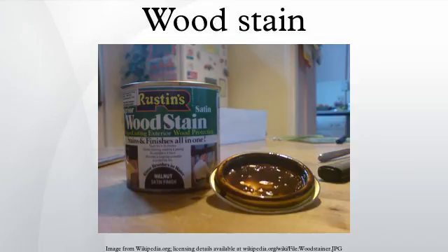Different wood stains are distinguished by the appearance they impart to wood. Certain solvent-based or oil-based wood stains contain small amounts of paraffin wax, which cannot be painted over, although restaining is still possible. Absorption: applying stains can be very easy or very difficult depending on the type of substrate, type of stain, and the ambient conditions. Fresh, green lumber accepts stain poorly, while aged wood absorbs stains relatively well. Porosity of wood can vary greatly, even within the same piece of wood.